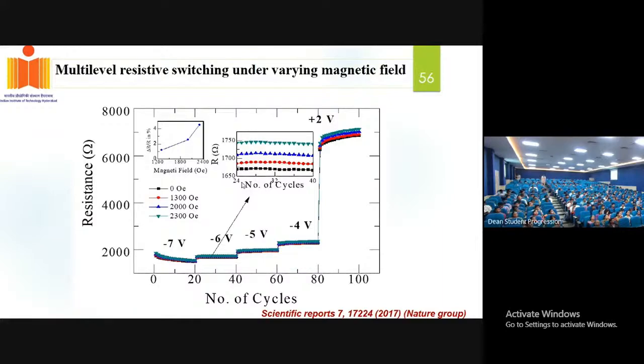So that means that nearly the delta R by R, the magnetic resistance ratio of 4% has been observed. So this is quite significant amount of value for the application of the magnetic field of the order of 2300 Oe. So this also proves that we could tune the resistance states of the device with the magnetic field without even touching or disturbing the device. In a remote way, we could tune the resistance states of the device with the magnetic field.